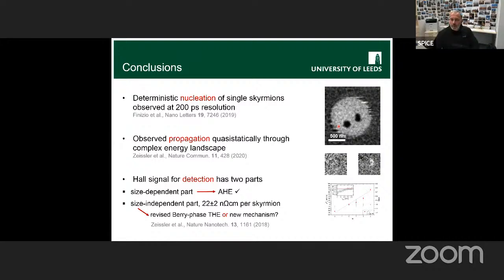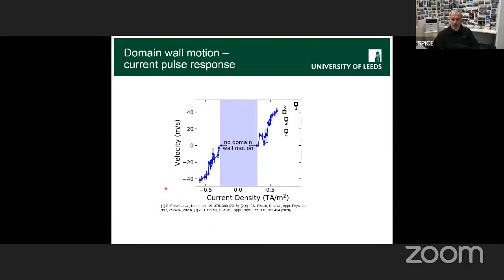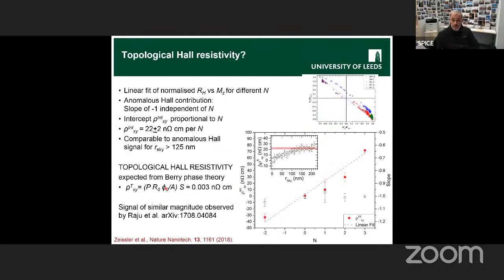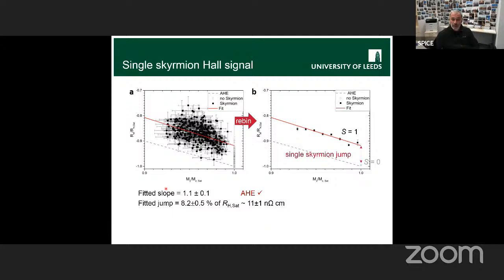So one thing that I wanted to comment on and ask you a little bit about is this anomalous Hall effect, where the topological contribution follows micromagnetics, which assumes adiabatic motion of the electrons following the magnetization profile, which wouldn't happen if there were just bubbles in this case. So you mentioned that there's a size-independent component that is not proportional to how the skyrmion is changing, right? In this case, in the analysis, did you identify that there's a finite magnetization component of it?